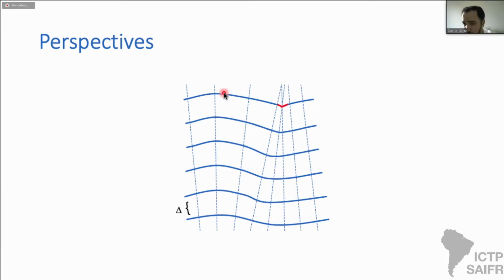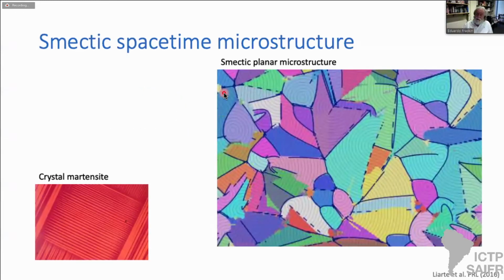Remember this figure I have shown at the beginning of my... Before we go to that, if you go back to your picture for the Martensite, you can see that they are strongly oriented along crystalline directions. Yes. Okay, so it's not true that you have continuous symmetry. It's not true because the long-range interaction introduces frustration. You can actually have non-trivial length scales in the periodicity, essentially. Okay, I see what you're saying. Ultimately, the regions actually are oriented along crystalline directions because those are the energy minima. And so you don't really have continuous symmetry in this case, as this picture shows. Compare the two pictures.